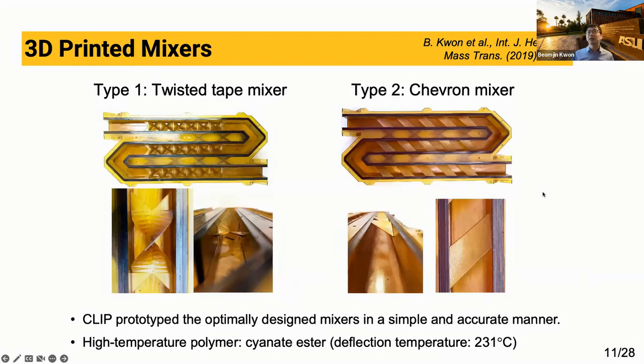So again, through the numerical simulations, we optimized the sizes and shapes of the devices. And by using a single 3D printer, we were able to make many different prototypes, but here I show only two cold plates. These photos show the top view and front views of the steady mixer inside the cold plate. From these photos, now you can see that the chevron mixers have a twisted parallelogram shape. And because we wanted to use this for heated surface, we employ a high temperature polymer, which can withstand above 200 degrees C.